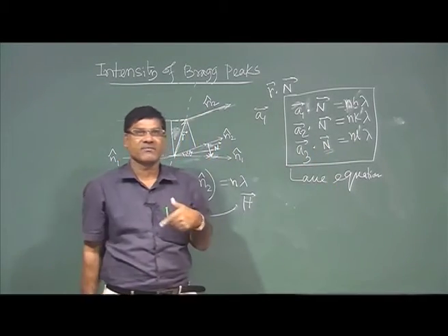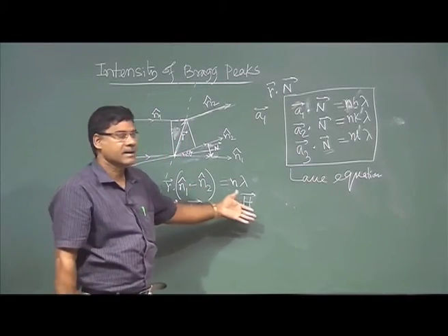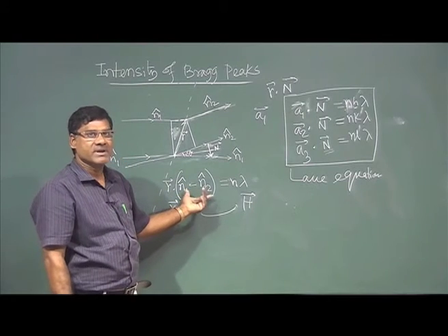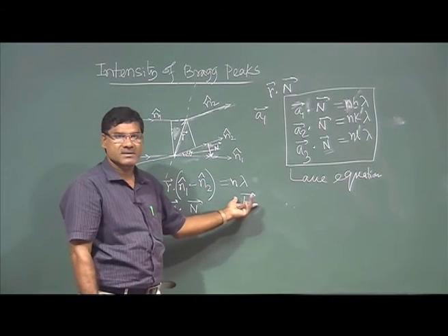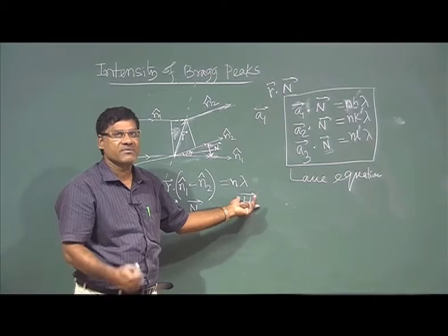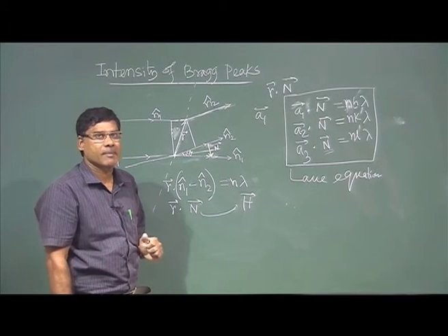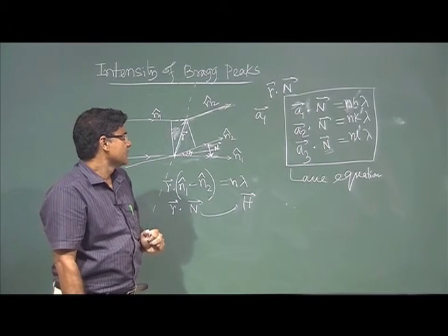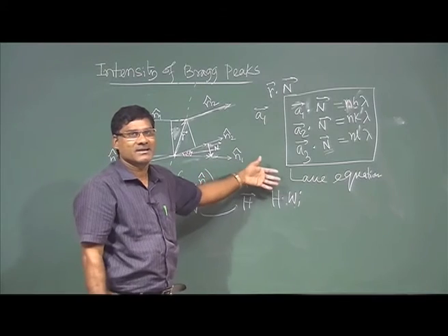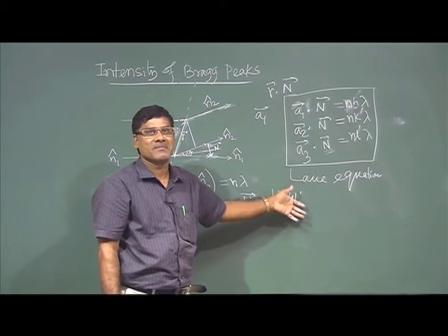So, this is the Laue equation, and since we now know the reciprocal lattice, this N, as I mentioned, one can replace with the reciprocal vector H, but as I mentioned, it differs in unit. So, the magnitude of H will be different, but direction wise they are the same. Okay. So, this is homework for you: just show that Bragg's law can be derived from this.